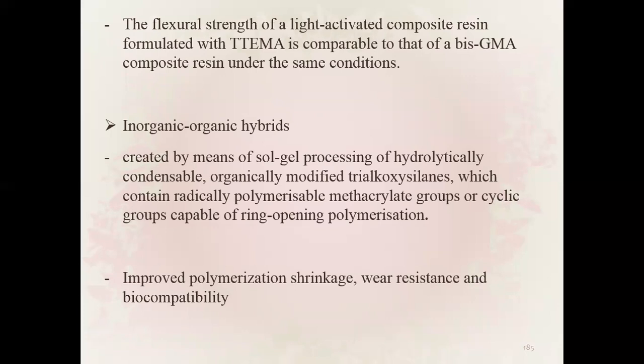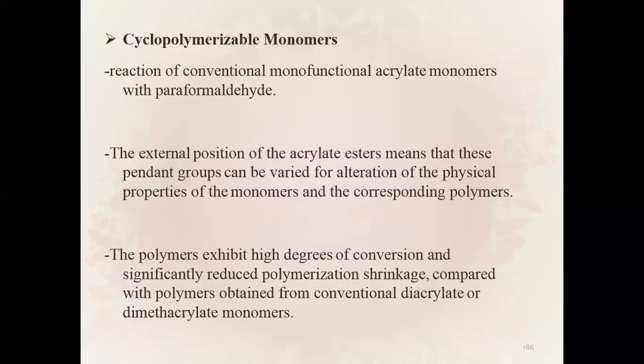Inorganic-organic hybrids are created by the sol-gel processing of hydrolytically condensable organically modified tri-alkoxysilanes, which contain radically polymerizable methacrylate groups or cyclic groups capable of ring-opening polymerization — improving polymerization shrinkage, wear resistance, and biocompatibility. Cyclopolymerizable monomers are the reaction of conventional monofunctional acrylate monomers with paraformaldehyde. The pendant groups can be varied for alteration of physical properties; polymers exhibit high degrees of conversion and significantly reduced polymerization shrinkage compared with polymers from conventional diacrylate or dimethacrylate.